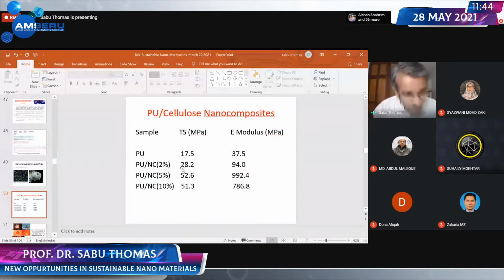Let me now show you one interesting work we have done with Sao Paulo University in Brazil. My counterpart in Sao Paulo University, Prof. Alcides, is very active in making polyurethane, medical grade polyurethane. So we decided on combining medical grade polyurethane with the nanocellulose. Look at the neat polyurethane modulus, 37.5. If you put 5% of nanocellulose from pineapple leaf fiber, look at this, 992.4. That's the beauty of nanocellulose.